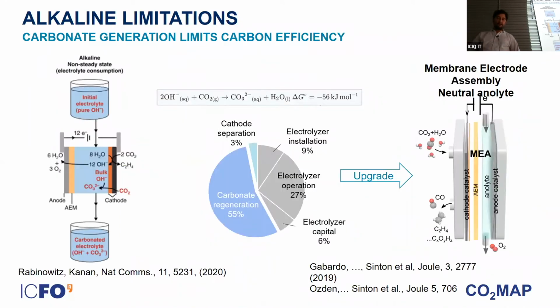for the generation of ethylene. Now, so far we have seen how we could improve the generation of hydrocarbons in electrochemical systems, in particular the generation of ethylene from CO2. We obtain high Faraday efficiencies. We obtain very high productivities. We obtain kind of okay energy efficiencies, not so high, but okay. But there is a hidden problem here. So we did that by using very high alkaline medium. And this is good because this improves certain aspects of the CO2 reduction reaction, such as carbon-carbon coupling and CO2 activation. But it comes with a consequence.